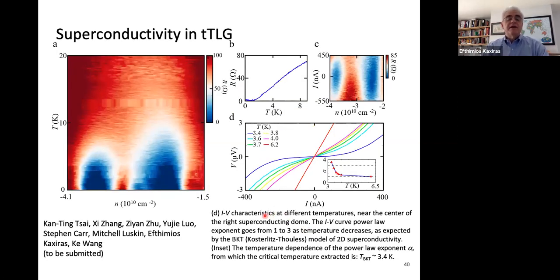Interestingly enough, our experimental colleagues, in this case, Ke Wang, who is a former postdoc of Philip Kim's, now a faculty member at the University of Minnesota, were able to produce such a system and make measurements of the different phases. So here's the temperature axis again, here's the doping, the number of carriers, and the dark blue corresponds to superconductivity. And this is shown schematically here where they try to measure the superconducting temperature that turns out to be about 3.4 degrees Kelvin, quite a bit higher than the bilayer system. And moreover, the twist angles are much larger here. So they're of order 2 or 3 degrees rather than 1 degree as the magic twist angle in bilayer graphene. So what is going on here?